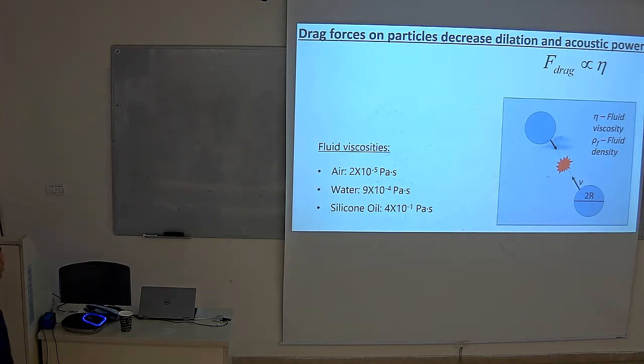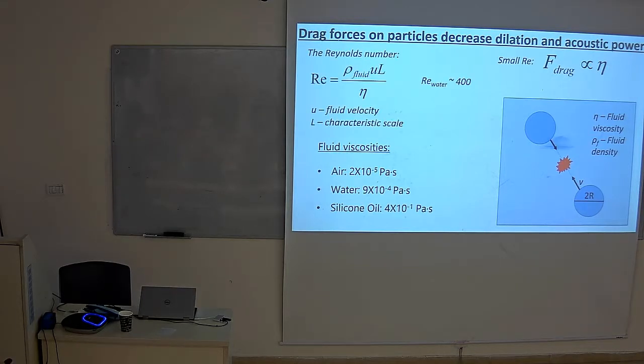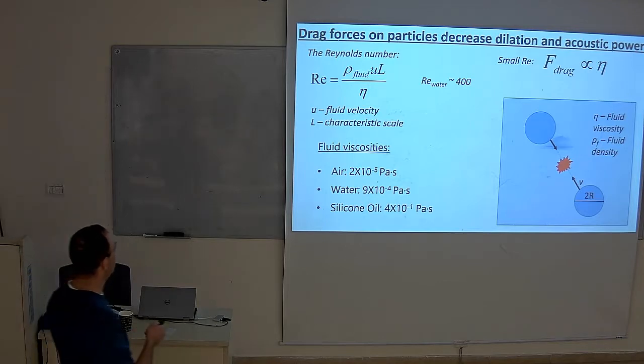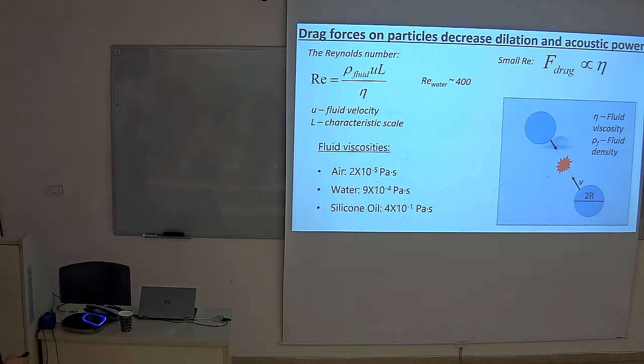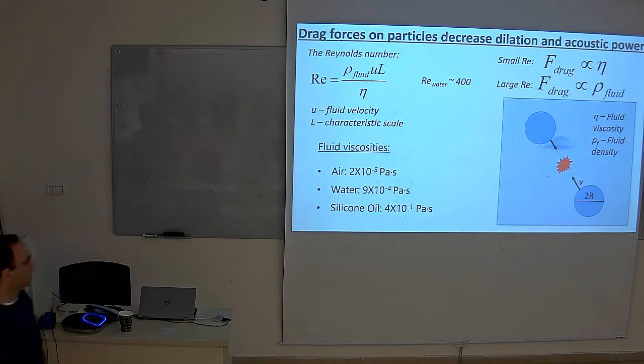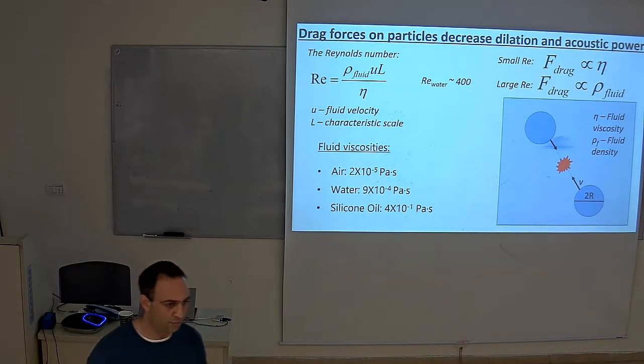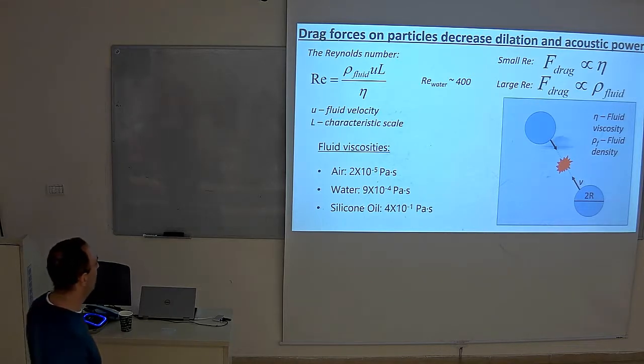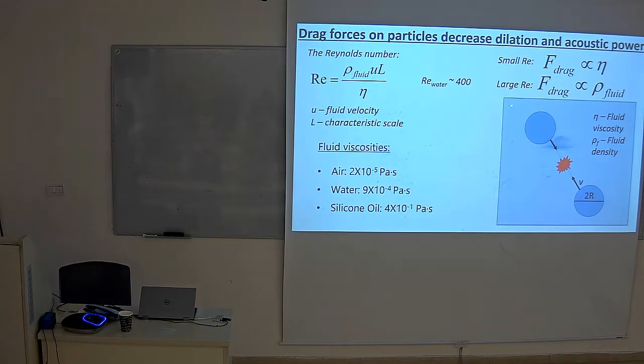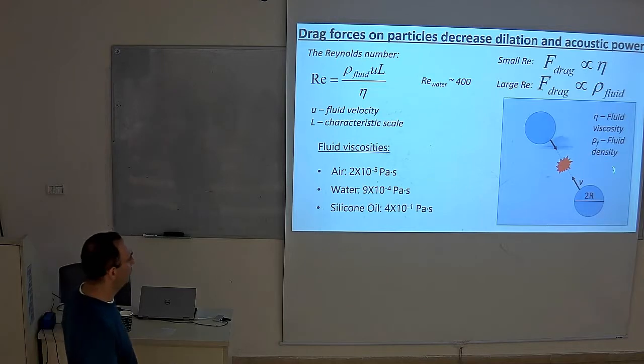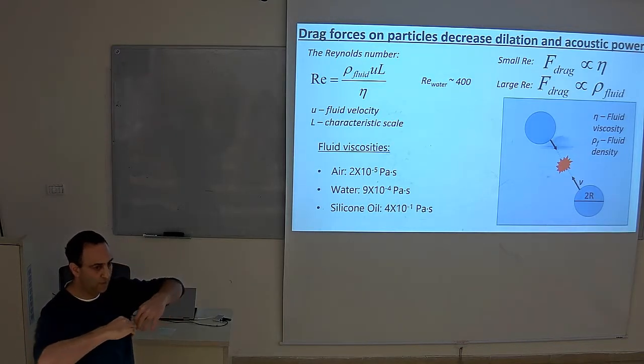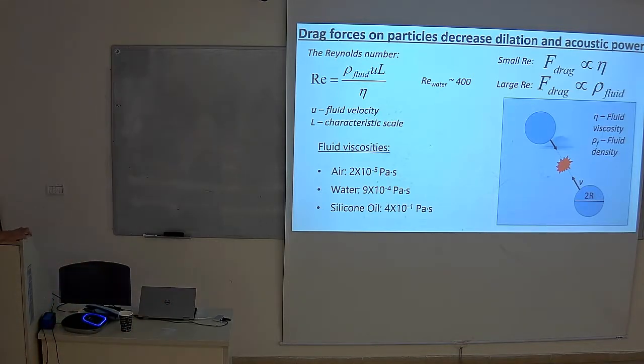However, that may be true, but if we are considering fluid dynamics, we need to consider Reynolds numbers. If we put in the densities, the velocity and the size scale, which is the grain size, we get a number of 400, which is a relatively high Reynolds number. A low Reynolds number is below 10. Something above 10 would not be relevant for this equation that is proportional to the viscosity. However, the drag force is also proportional to the density, in a different equation and in a different way. And the change in density between air and water is very important. It's 3 orders of magnitude different, and therefore the same idea of reducing the velocity between the impacts can be the case also here.